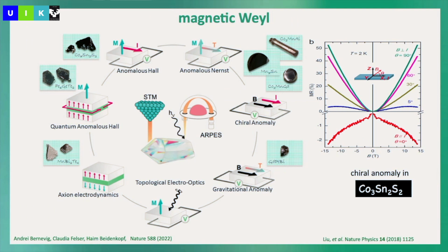So the nice thing is, and this is simply as an idea, if you have a Dirac semimetal, you can strain the Dirac semimetal, you reduce the symmetry, you remove inversion symmetry, then you can turn a Dirac semimetal into a Weyl semimetal. But the other way to make Weyl semimetals is to break time reversal symmetry. And this is nice, because this is an even bigger field where I think there's still a lot to do: the magnetic ones, because if you make something magnetic, every crossing point in the band structure is a Weyl point. So there's really an inflation. More or less every compound can be turned into a Weyl semimetal by doping the Fermi energy to the right position. And this is really where you can have many interesting properties, despite the chiral anomaly, which we showed also for some magnetic material, and the gravitational anomaly.